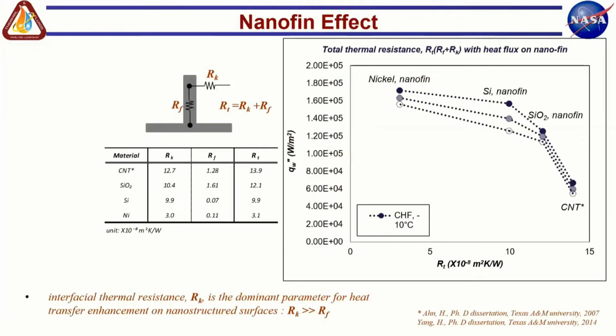So we pitched this idea to NSF. They took a risk on us, and thankfully, we got a grant to test out this hypothesis, and we did the experiments. And sure enough, carbon nanotube gave us the lowest CHF. Glass nanofins actually gave us better CHF enhancement than carbon nanotubes. And of course, nickel actually performed a lot better. And if you notice, this curve is not on a straight line. You're sort of seeing a saturation curve.